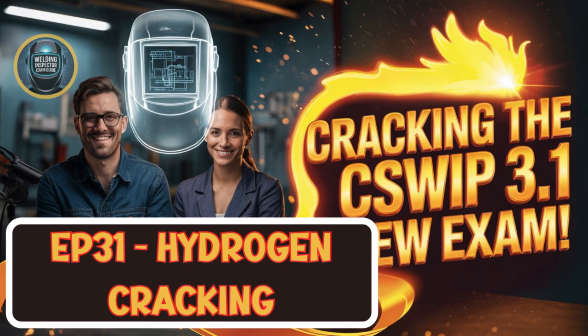Okay, so it's like a four-legged stool, take one leg away and it falls over. Precisely. And often, dealing with the hydrogen is the most direct leg to target, but the others are just as critical, especially with tougher materials or tricky designs. Right. So what are the four ingredients for this perfect storm? What needs to be present? Okay, number one, you need enough hydrogen. The threshold is generally considered to be above 15 milliliters per 100 grams of the deposited weld metal. 15 milliliters per 100 grams. Got it. That's the hydrogen level.